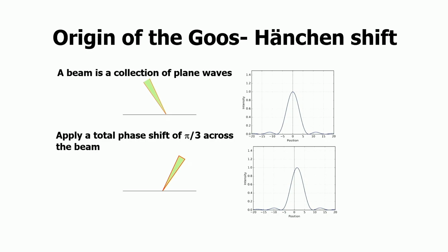This is possible if you have an oblique incidence of a beam. Instead of a circular spot, which is incident at an oblique angle, it becomes elliptical. There is a phase accumulation from one end to the other end, which is possible in such oblique incidences, and that leads to a shift in the centroid of the beam. Right. So in plasmonic structures, when a beam is incident at an angle on the structure, the plasmon mode is excited and then it's re-emitted into the far field. The plasmon coupled shift is pretty large, and people have shown up to a few microns of these shifts.